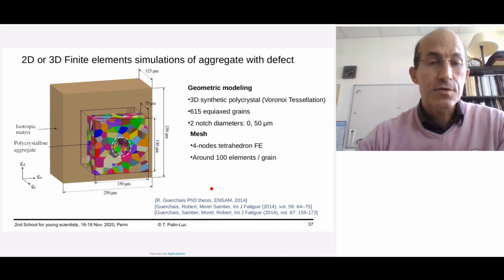So the results are either in 2 dimensions or in 3 dimensions. I'm presenting here, because of lack of time, only 3-dimensional finite element results on aggregates. So you can see here a polycrystalline aggregate with a defect in the middle. To avoid parasitic effects due to the boundary conditions on the polycrystalline boundary here, this volume is embedded in an isotropic matrix, which is elastoplastic. And then the boundary conditions to simulate either tension or shear are applied on the free surface of this volume.